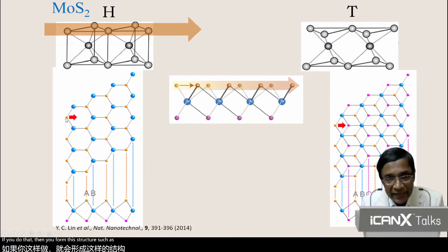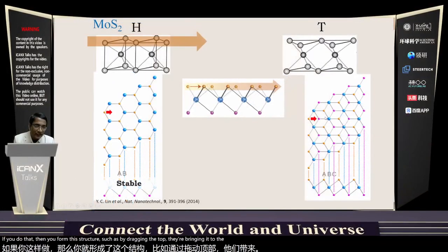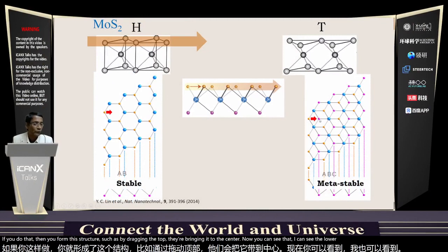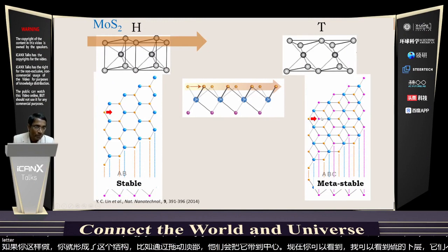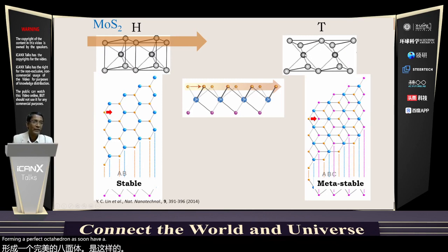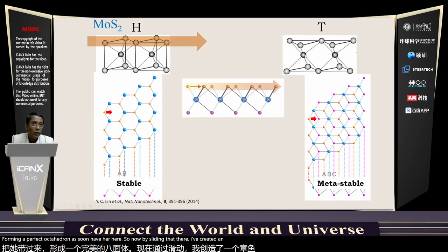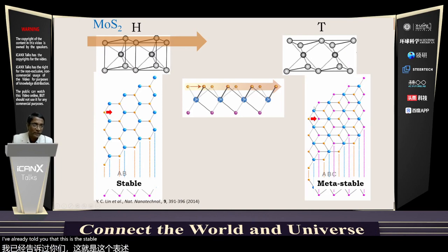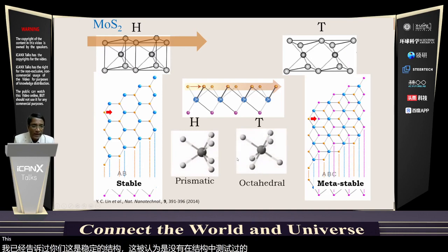So just by dragging the top layer, bringing it to the center, now you can see that I can see the lower layer of sulfur, they're not eclipsed anymore. And you see that around the molybdenum, 3 sulfurs from the original layer on top, the 3 sulfurs below, forming a perfect octahedron as shown over here. So now by sliding the layer, I've created an octahedron of MoS6 unit from a MoS6 prismatic unit. I've already told you that this is the stable structure, and this is believed to be the metastable structure. This is prismatic, this is octahedral.